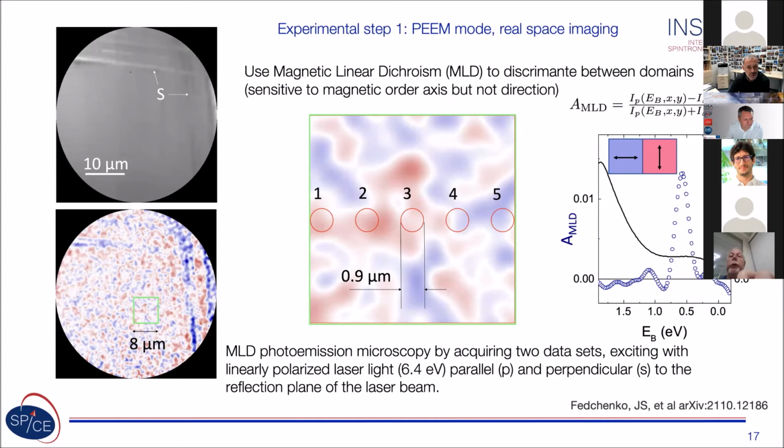So these orange regions, I just blow it up here on the right, and even look closer at regions 1, 2, 3, 4, and 5, which in the experiment itself, that's what Jairo was able to do, by restricting the aperture, could actually focus directly on these regions 1, 2, 3, 4, and 5, or whichever ones you choose, which are 1 micron size domains that seem to be monodomains, and to see if they are in fact monodomains, and be able from there to only observe the photoelectrons arising from these restricted regions instead of the entire larger region, which you would do in the momentum ARPES experiment.